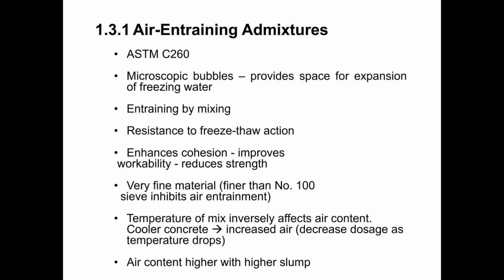All right, so the first admixture we're going to discuss is air entraining admixtures. These are covered by ASTM C260. The way these admixtures work is they introduce microscopic bubbles into the matrix of our concrete mix. Those bubbles then provide space for expansion of freezing water. So air entraining is very effective in helping to minimize the amount of damage that occurs due to freeze-thaw cycles. As a result of that, we see air entraining specified more commonly in areas where, due to the environment, the concrete is going to see a higher number of freeze-thaw cycles.